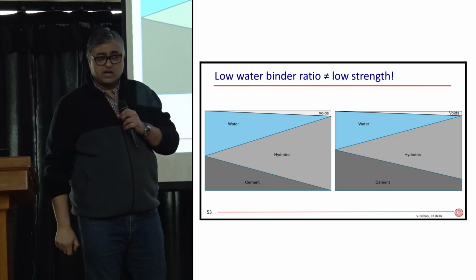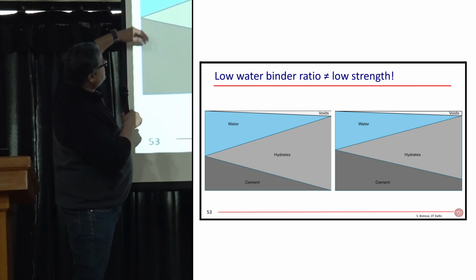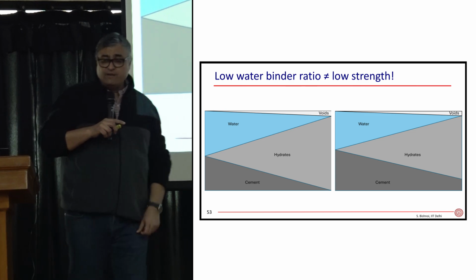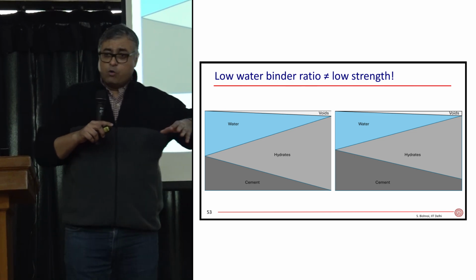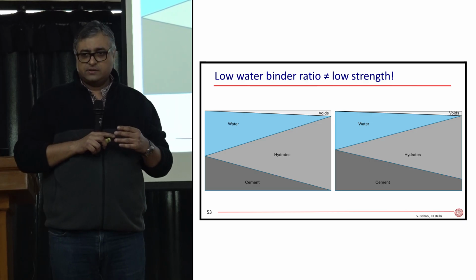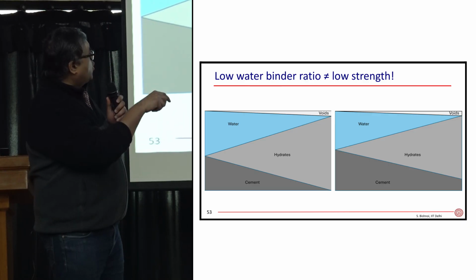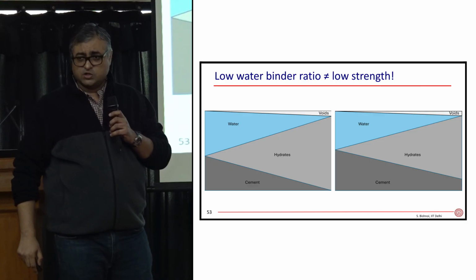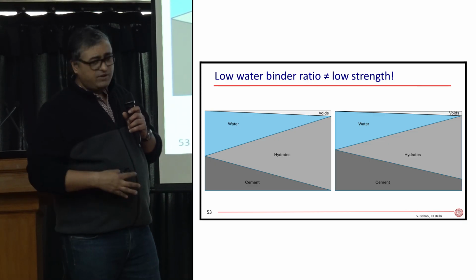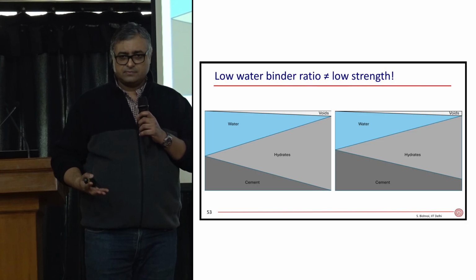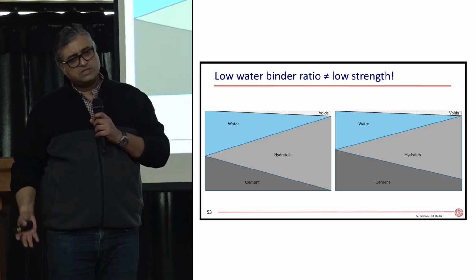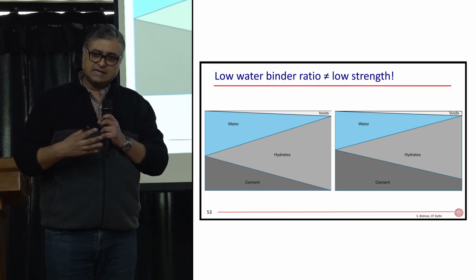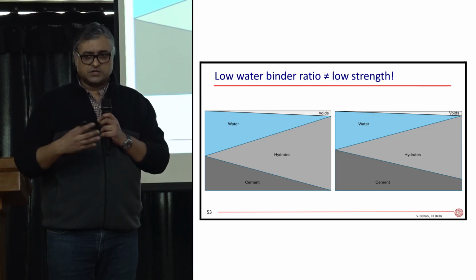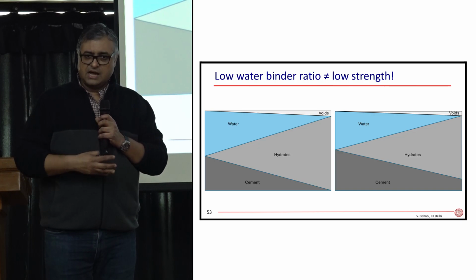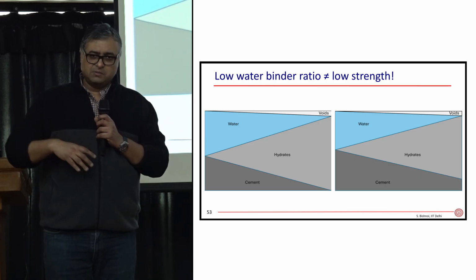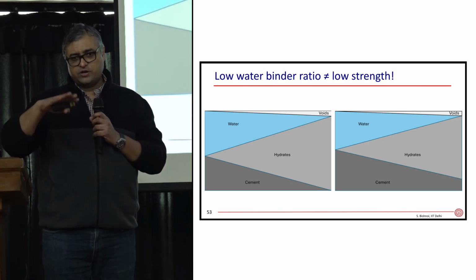If you had a water to binder ratio higher than that, you had less cement and more water, you would have water left behind and no cement left. You would have more pores left behind because of that. Pore is everything that has water and is empty inside the concrete. If you have more pores left behind, you end up with something weaker, also more porous, more permeable, allows anything to come in from outside, less durable as well. That's why a higher water cement ratio is bad.